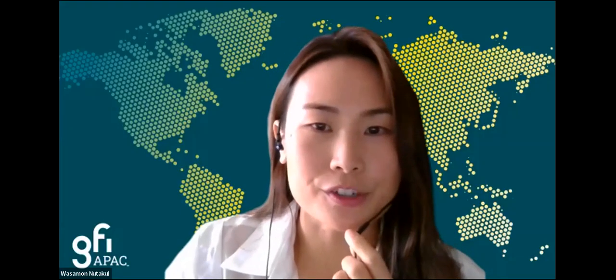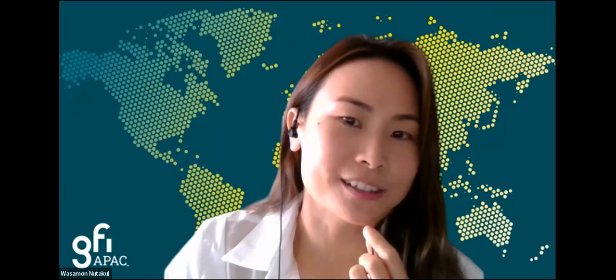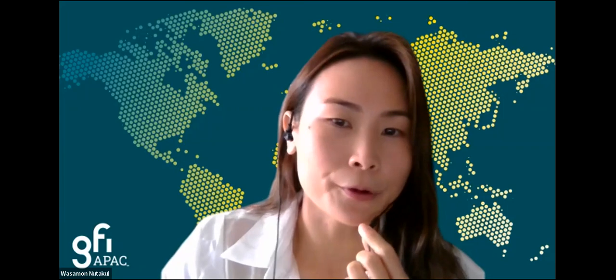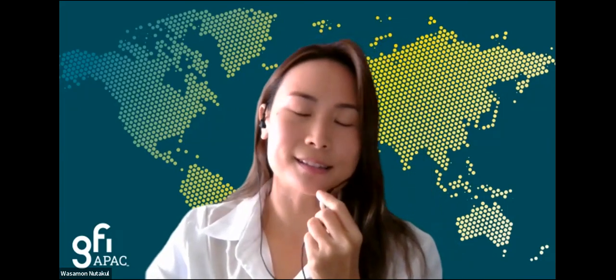And I think this relates to the previous question: how does the oil content in raw material impact the fiber formation? Is it important when producing texturized product from oil industry byproducts, like the oil press seed cake? Yeah, that's a very important question, and that is to our understanding very relevant. The oil is not so much about the effects of taste or aroma, but more about the viscosity during the extrusion process. High amounts of oil are difficult or do prevent this fiber formation process, because it reduces the viscosity and the shear forces during the process, so that the phase separation cannot occur to the extent required for fiber formation. So therefore, this is a challenge.